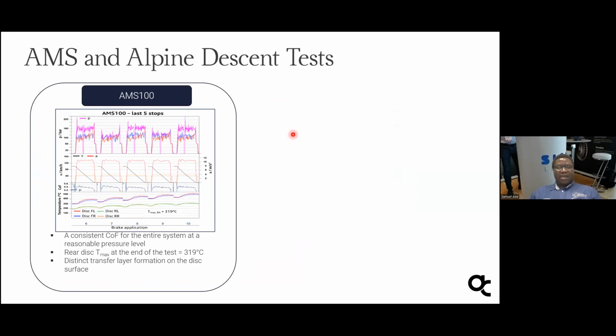And here are the AMS and the Alpine descent results. From this AMS 100, here I show the last 5, because as I've said earlier on, there are 10 consecutive braking events, but I chose to show the last 5. You see the pressure applied is almost above 180 bar. We also see the coefficient of friction here is stable, almost in the same range in the last 5, that is from braking application 6 to 10. So it's much more stable, which is very, very good. The maximum temperature obtained for the rear disc is around 319, which is good. And we also see that the transfer layer is very, very good as well.